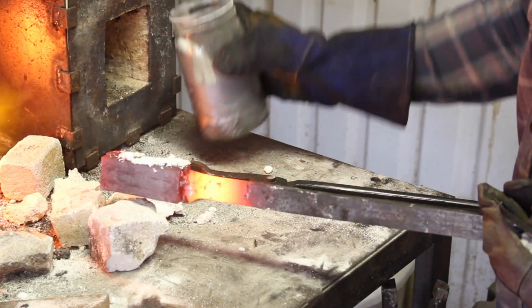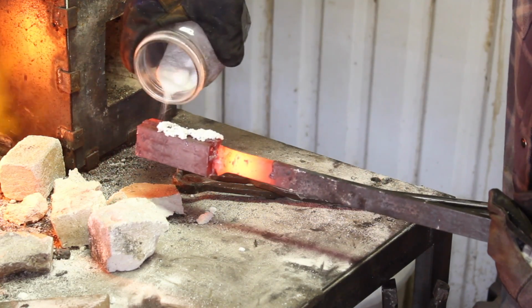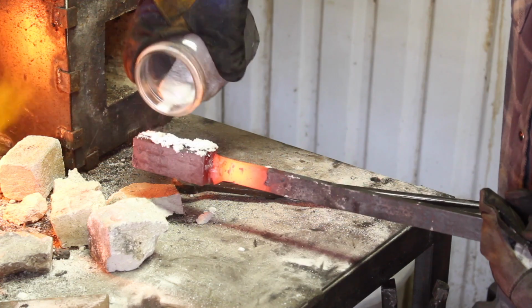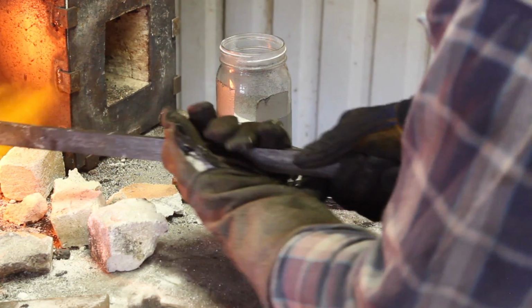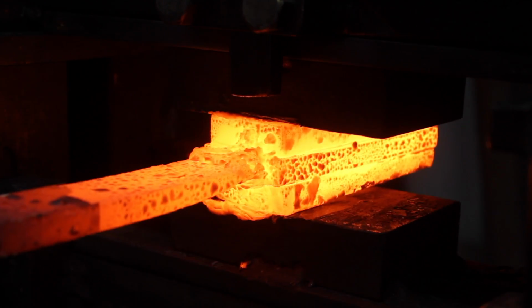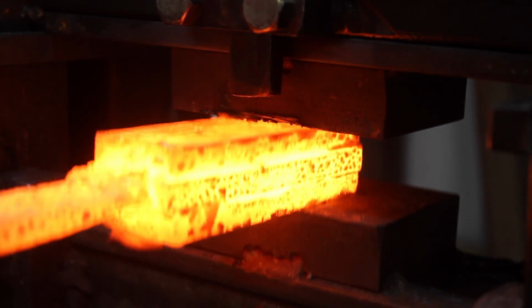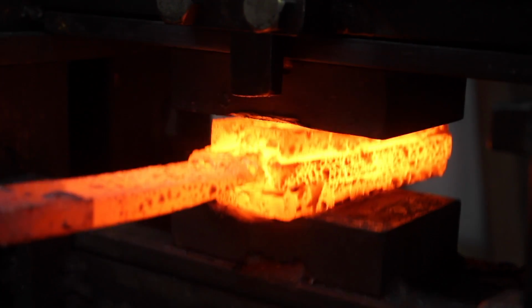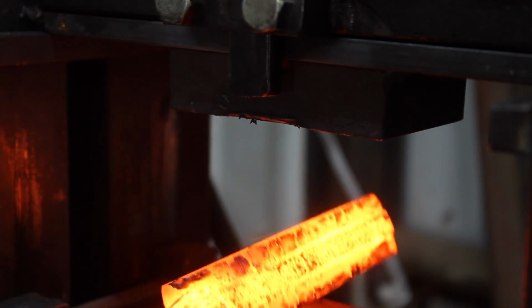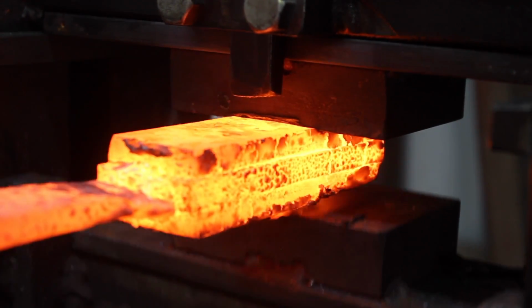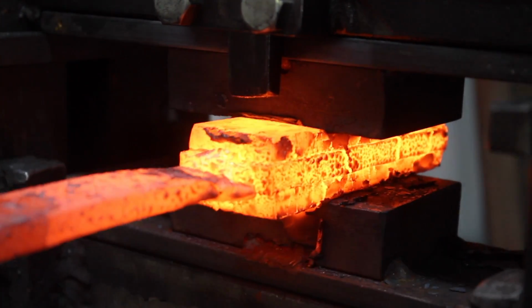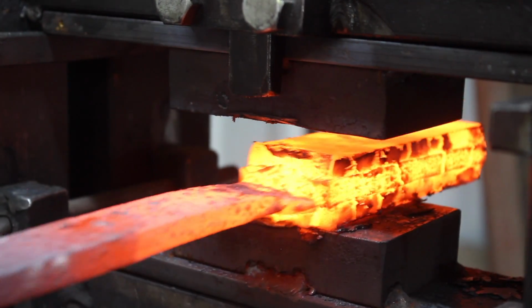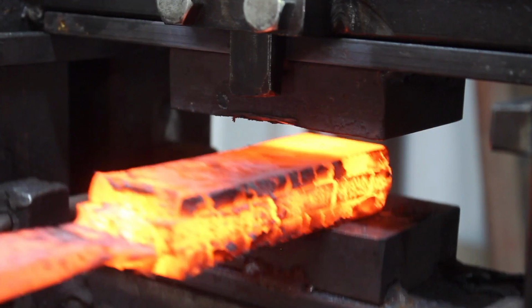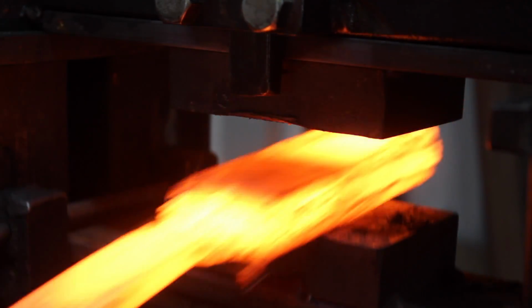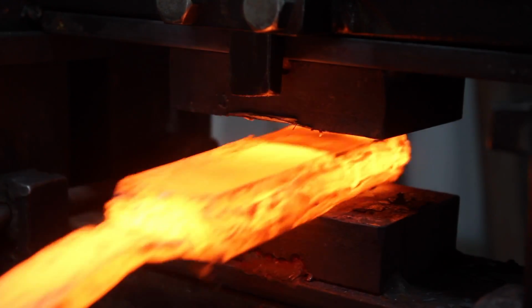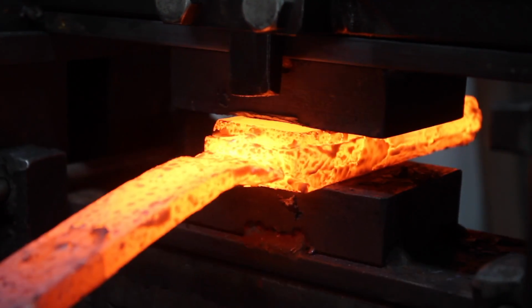You'll notice that the billet here is just at a red heat, not even quite, and I want to put flux on there as quickly as possible. It's not able to fully melt it yet, but getting that on there as soon as possible is best in my opinion. You can see how that opened up there, but because there was flux on those surfaces and I was working it from front to back to squeeze out that flux and impurities, we got that almost completely closed up and welded. Just a little spot there that I had to readdress, and we're getting it closed up right there. So that gives you an idea of why we do things the way we do.